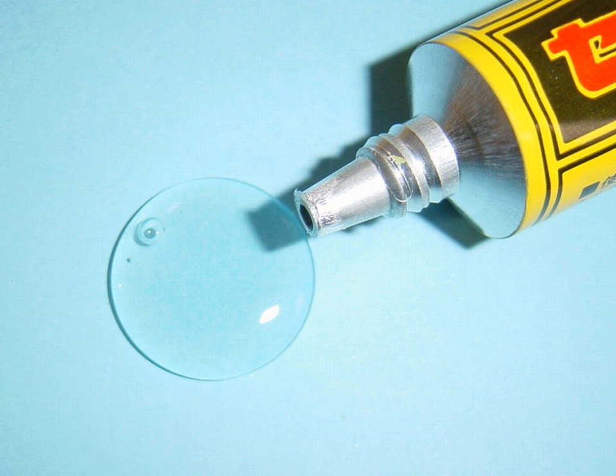Fracture can also occur in the adherend if the adhesive is tougher than the adherend. In this case, the adhesive remains intact and is still bonded to one substrate and remnants of the other. For example, when one removes a price label, the adhesive usually remains on the label and the surface. This is cohesive failure. If, however, a layer of paper remains stuck to the surface, the adhesive has not failed. Another example is when someone tries to pull apart Oreo cookies and all the filling remains on one side. This is an adhesive failure, rather than a cohesive failure.